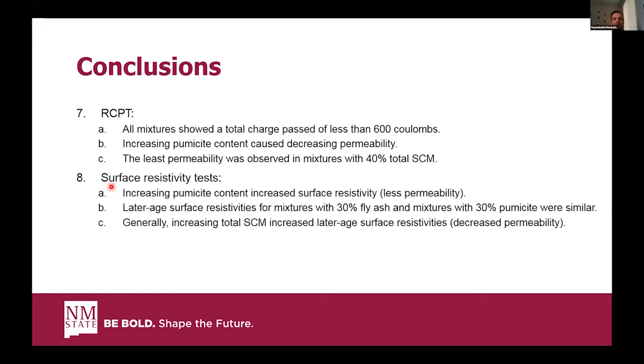For RCPT, we found that the total charge passed based on ASTM C1202 was less than 600 coulombs, which puts them in the very low category. I mean, the penetration was very low. And the permeability decreased with increasing the pumicite, and they became closer to the negligible area. And the mixtures with the greatest amount of SCM, which was 40%, I mean 20% fly ash and 20% natural pozzolan, had the least chloride permeability.